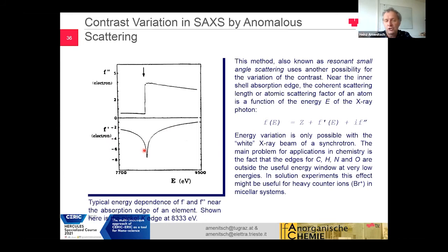If you have core shell particles and you want to learn about the constitution of the shell, you can tune selectively to one part, the shell or the core, the electron density contrast, and by comparing different electron density contrasts from measurements at different energies, you can find out where what is sitting, either one component in the shell or one component more in the core.